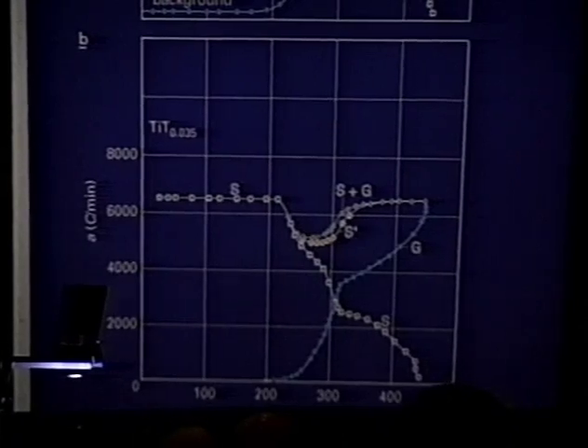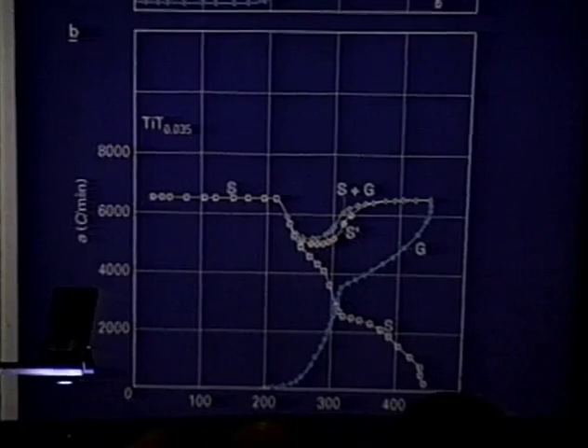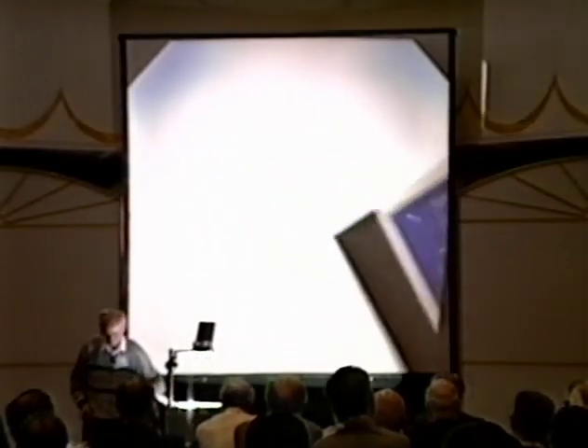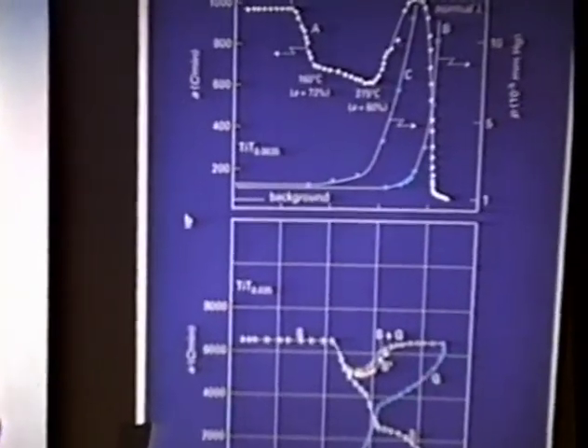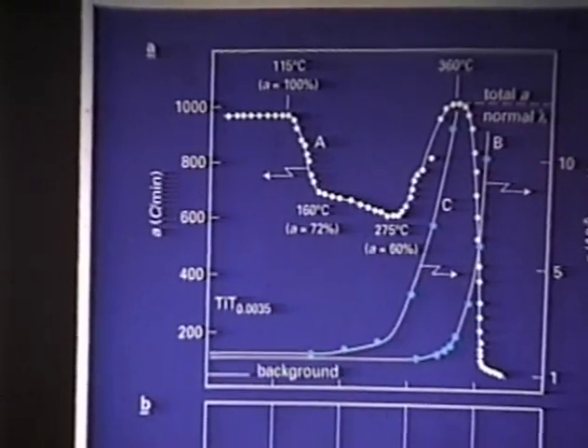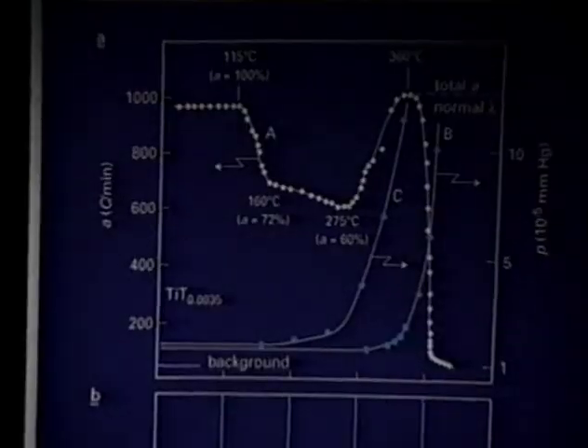It is very important that this experiment is done under a very different condition, with a decreasing concentration of our preparation, and the concentration at the minimum of the radioactivity at 275 degrees centigrade is 8.5 times higher than with the first experiment. It can be shown that the course of these two experiments is equivalent.